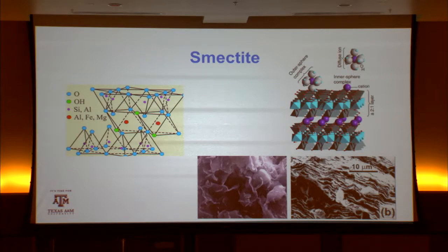Then we move over to the real problem, the smectite clays. So once again, these smectite clays are composed of layers. In this case, here's the silica tetrahedral layers. You can see the silicon, the purple in the middle, the oxygen, the blue on the outside. We got a layer up here, a layer with peaks pointing up down here, and in the middle you've got your aluminum octahedral layer. So you've got these materials that are composed of oxygen, silicon, and aluminum, the 3 most abundant elements in the crust of the Earth by far. So it's no surprise that they comprise these structures for clays.